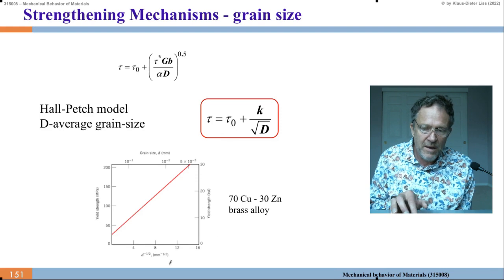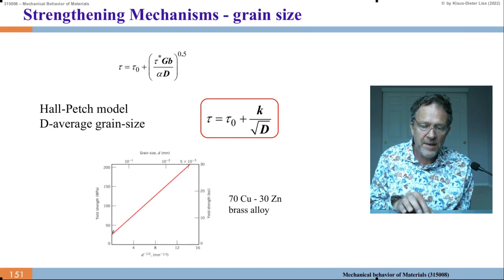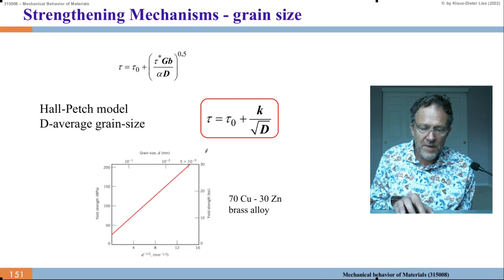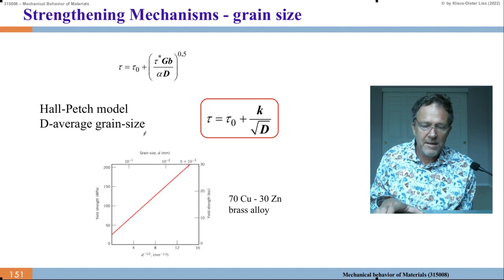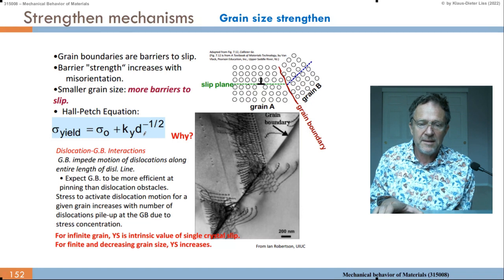So if 1 over square root D goes to 0, that means the grain becomes big, big, big. So we don't feel a grain size effect anymore. Then we just have the deformation strength of a large bulk single crystal, which is weak. And as we make the grain size smaller, we see it increases linearly with 1 over the square root of D. This is the Hall-Petch model, and it applies for a large class of materials.